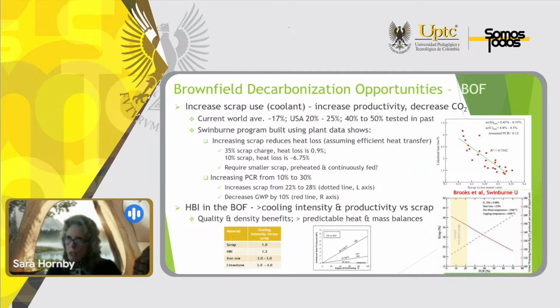This is going to require smaller scrap, probably preheated and continuously fed as opposed to a big bucket dump. Also, if you increase the post-combustion ratio from 10 to 30% on this bottom graph, then you're going to increase the scrap from 22 to 28%, this dotted line, and you're going to decrease the global warming potential following this red line by 10%. Also, HBI in the BOF is going to give you a greater cooling intensity and productivity versus scrap, as you can see from the chart at the bottom and the table.